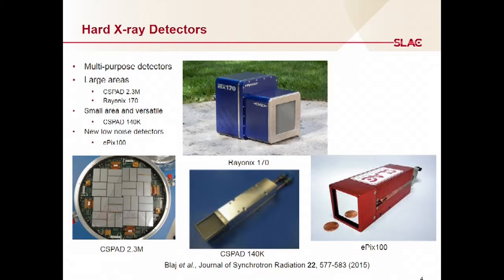And so we have specially developed detectors that were built for us, such as the CSPAD. This is a 2.3 megapixel detector, which can run at 120 hertz. It has single photon sensitivity, which means it can detect a single photon, as well as a reasonable dynamic range, which means it can detect several hundreds, maybe even thousands of photons, depending on the photon energy. There are Rayonix, this is a scintillation detector, which can run at 30 hertz, but is also very good if you need really high dynamic range. So if you anticipate very strong signals, like very intense Bragg peaks, this is the detector that you would use for that.